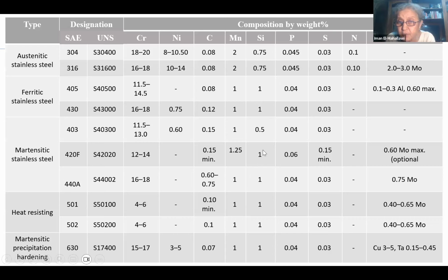For example, you can see here it's 0.03 in some of them and 0.15 in another, so we have to abide by these concentrations. Usually these are not alloying elements. They are harmful elements, or what we call tramp elements, and they should be avoided. Some of the contents, like the manganese and the silicon as well, should be kept within the range required by the designation, because if they exceed it, they will be harmful again to the main properties that we are seeking.